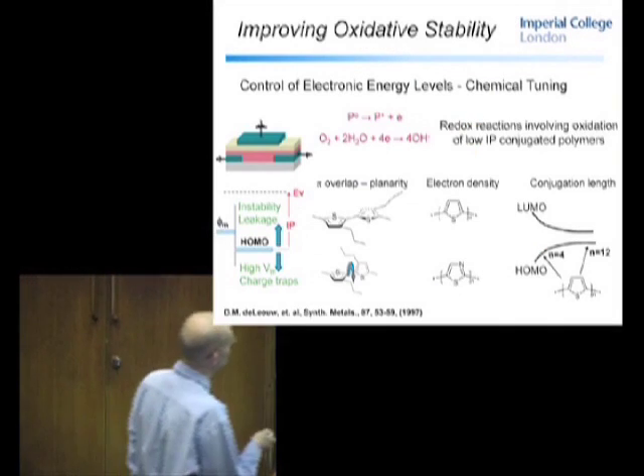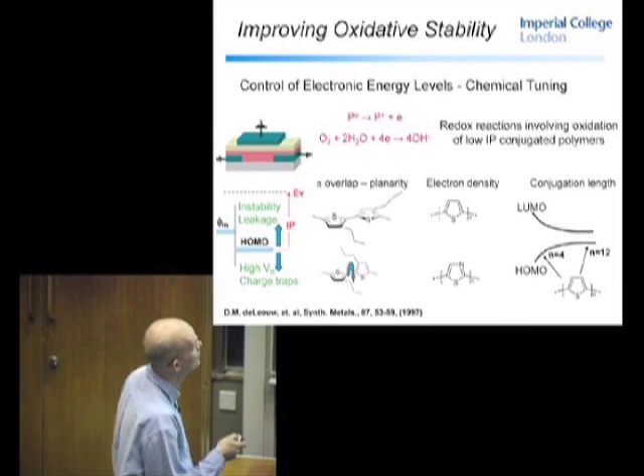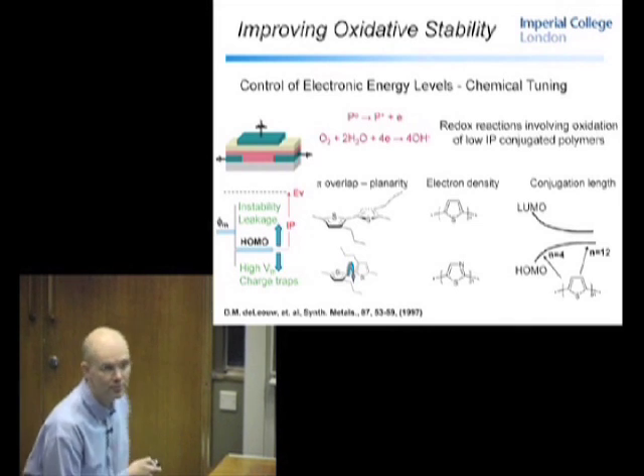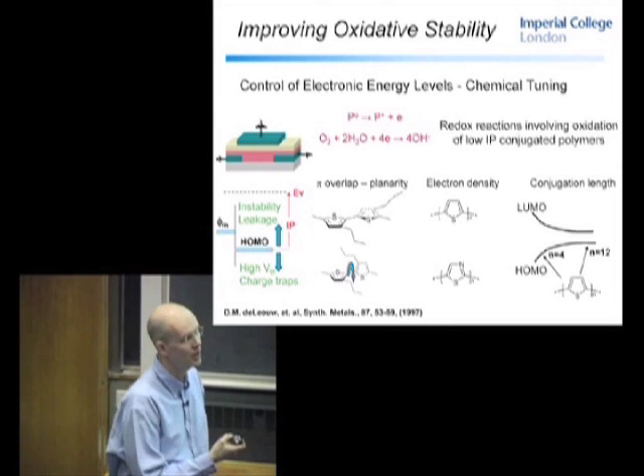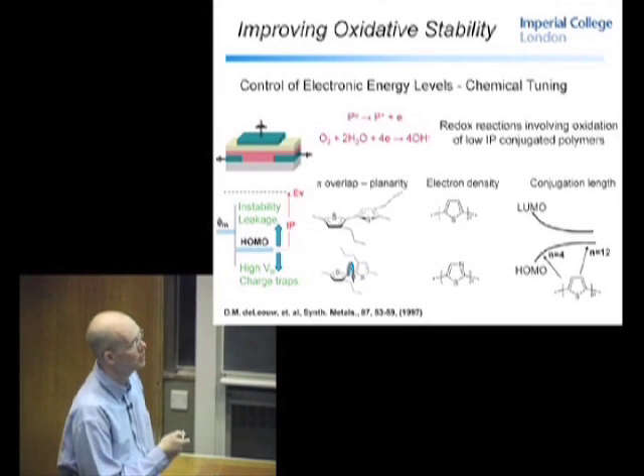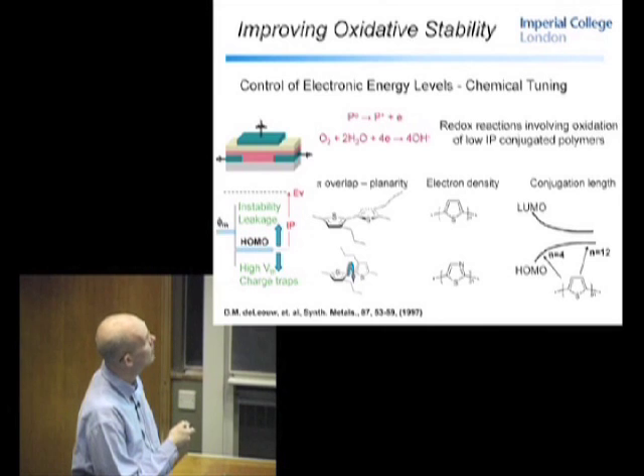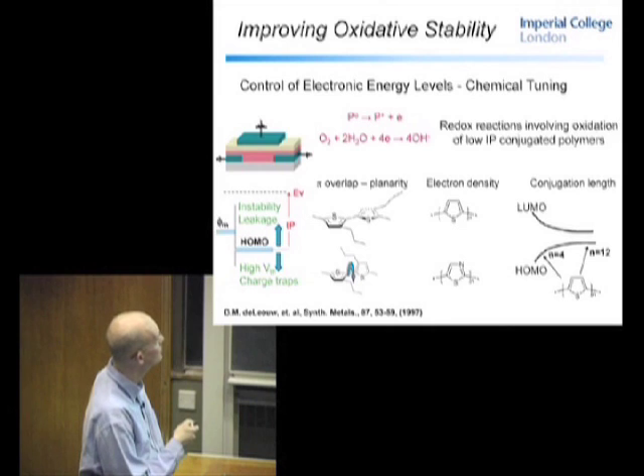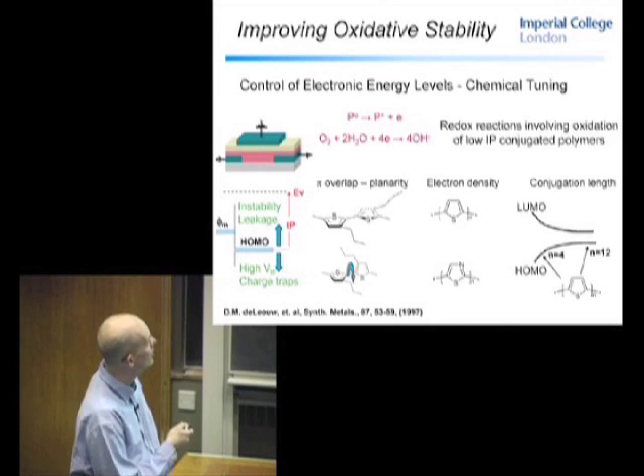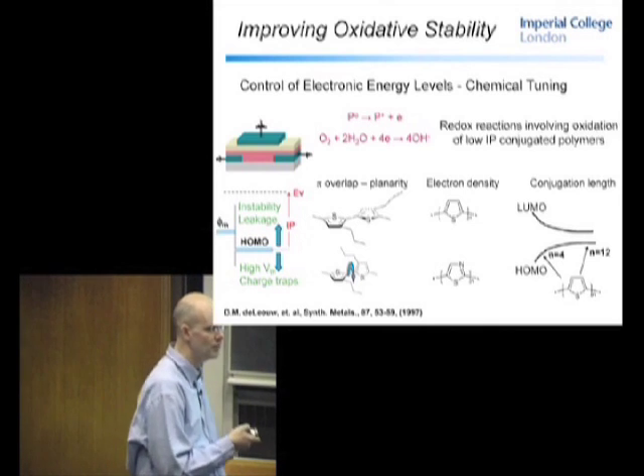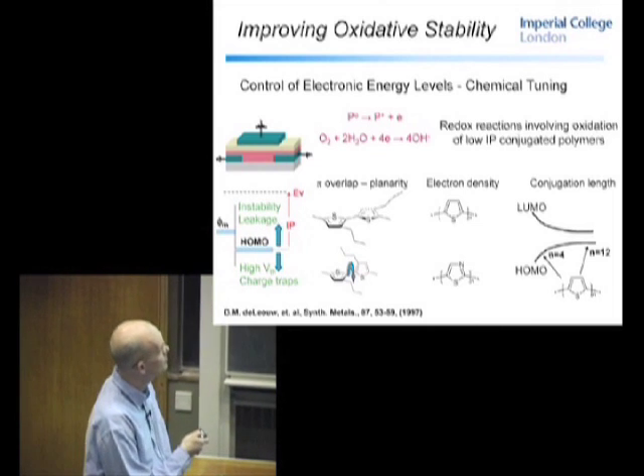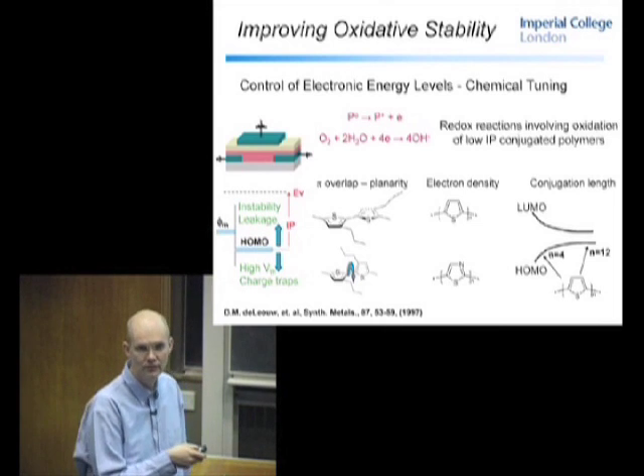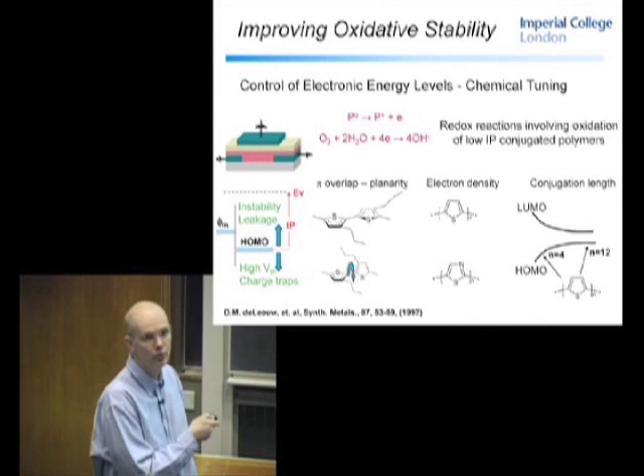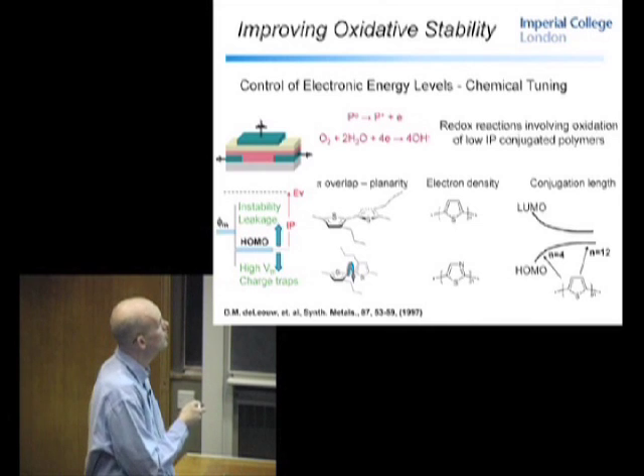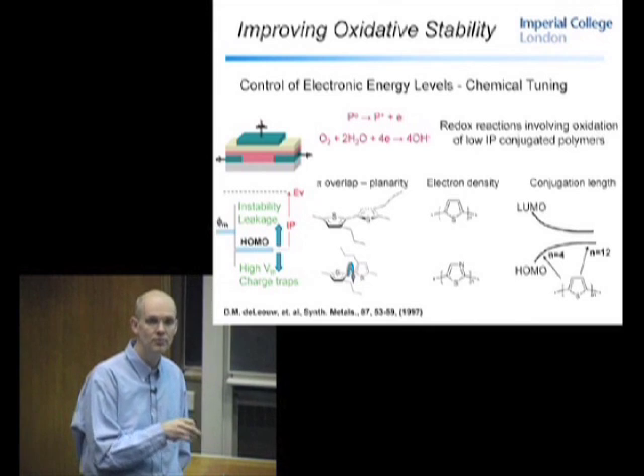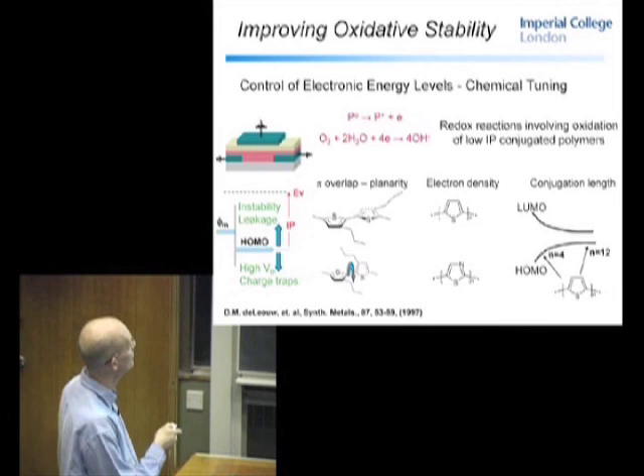And so I'll get to the second point, which is trying to achieve higher ambient stability. What I'm showing here is one of the primary redox reactions that occur. This is an electrochemical, so it's a thermodynamic electrochemical process that occurs in the presence of a polymer. So the polymer is oxidized, loses an electron, in the presence of oxygen and water. So this is a sort of forward two reactions that will occur. And this is an exothermic process when the ionization potential of the polymer is around 4.9 to 5 electron volts. That's when you assume you've got a saturated water environment, so it really depends on the relative humidity here. But basically, if you have an ionization potential of less than that, you've got to be a little bit worried that you're going to have oxidation in the presence of water, or the combination of water and oxygen.